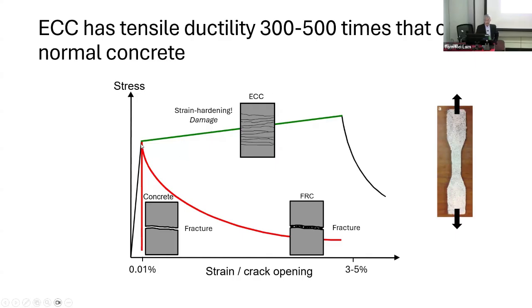In ECC, we have this funny behavior. You have an elastic stage, and then it undergoes strain hardening, tensile strain hardening. And you can see that despite the damage that I show here, the material's load carrying capacity continues to rise. And how far does it go? Well, for this illustration, it shows about 3 to 5%. We can actually do even more than that. 3 to 5% is very large strain deformation. That's the reason why you saw that bent specimen smiling at you in that shape.